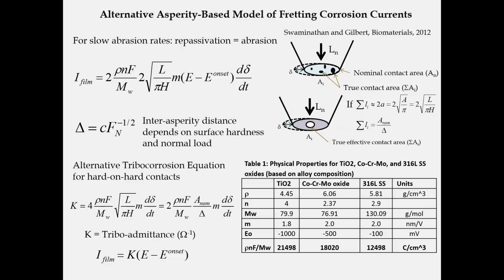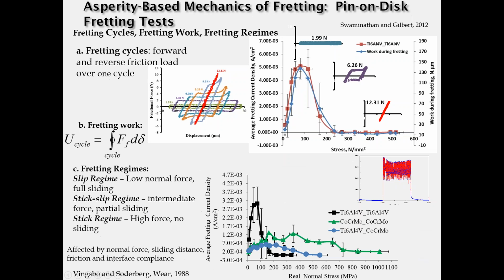And again, it's important to note that there are these recurring parameters, ρnF over molecular weight. This is a sort of Faraday-like constant, which tells you how much charge in coulombs is associated with a volume of oxide formed. And this is very useful for us to make estimates based on the currents that we measure of how much oxidation has taken place. And because, again, we have this ability to control or measure most of these parameters, we can be very quantitative in these kinds of measurements.